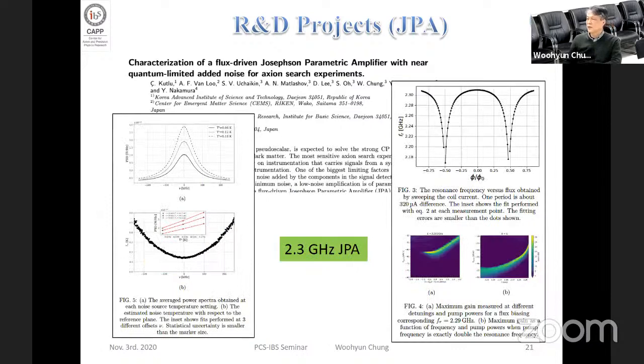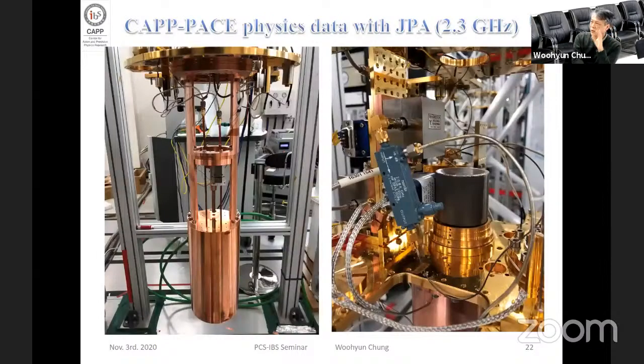Another JPA we tested was the 2.3 gigahertz JPA. It didn't reach the standard quantum limit yet, but it was good enough for us. If you read it, it is very small, but our noise temperature was around 120 to 130 milli-K, which is very nice. So we put it in our Axion experiment. We took the HEMT out and installed our JPA. You can take a look here. This is the JPA shielding. Later we put it upside down, but this was the initial picture.